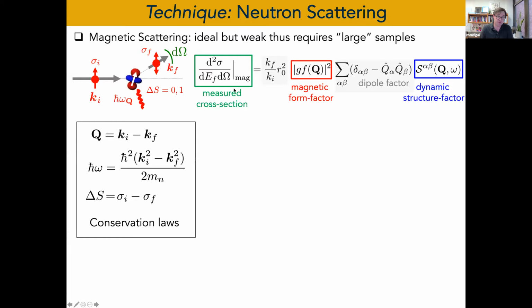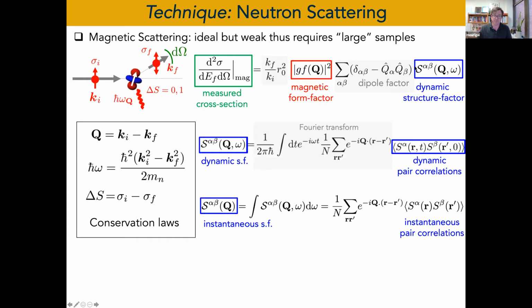And of course, the beauty of the technique, in some sense, what we are using a lot in the project that we'll show, is the ability to connect with theory, because the cross-section, what we measure in the detector, is directly related, up to geometrical factors and something that has to do with the form factor, the orbital in which the magnetic moments are living. But up to these material-dependent geometrical constants or parameters, if you wish, the technique directly measures the dynamic structure factor. And that quantity, you can understand it in several ways, but a simple way to understand it is that it's a Fourier transform in time and space of two-point correlators between spins.